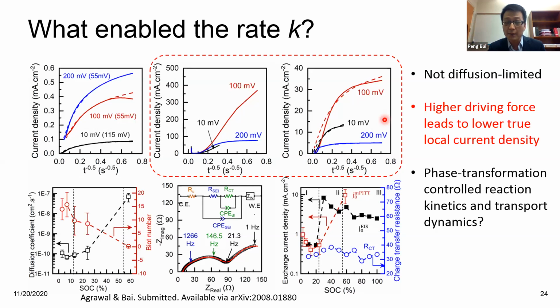The first level is how many particles you can activate. You can trigger them to participate in the reaction. And the second level is that this excitation will also control the phase boundary propagation within each particle. So that is why we should really call it phase transformation controlled.